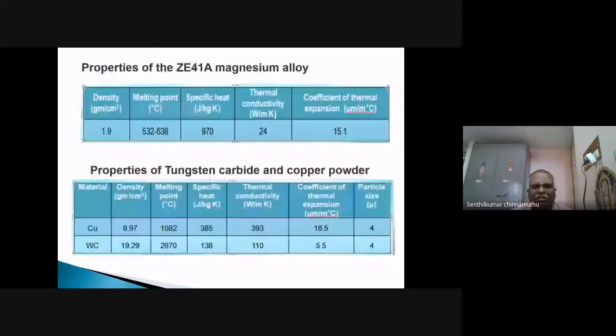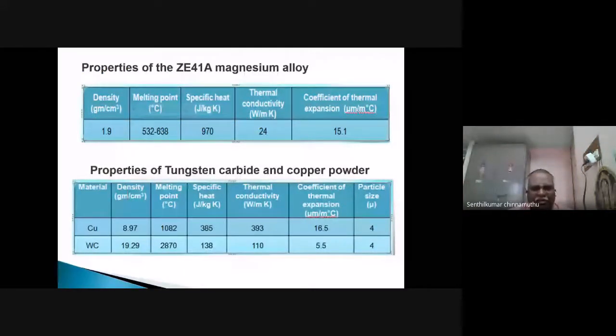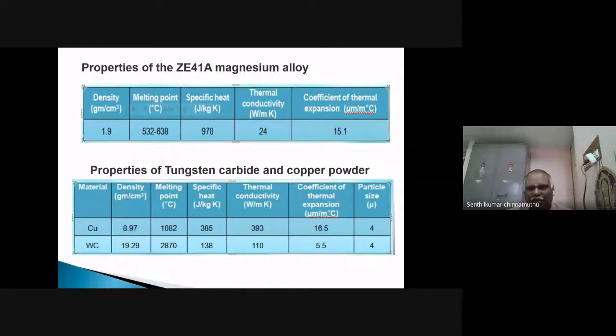The properties of ZE41A magnesium alloy are a density of 1.9 gram per centimeter cube, melting point of 532 to 638 degrees Celsius, specific heat 970, thermal conductivity 24, coefficient of thermal expansion 15.1. And the properties of tungsten carbide and copper powder.